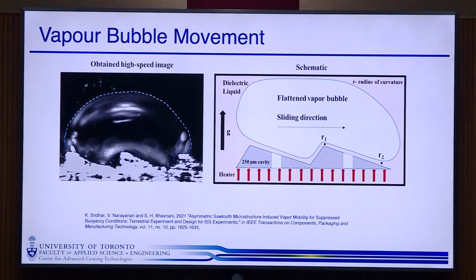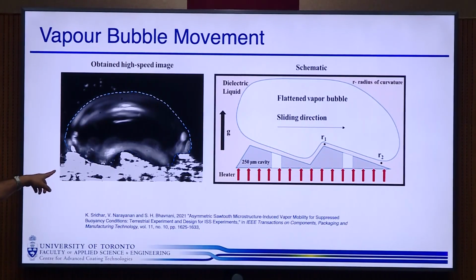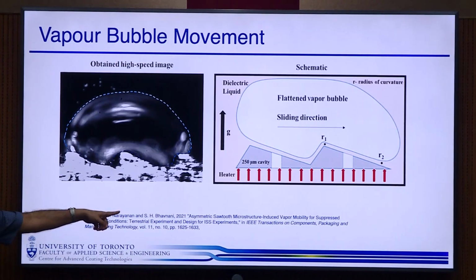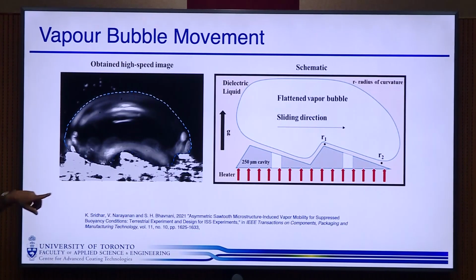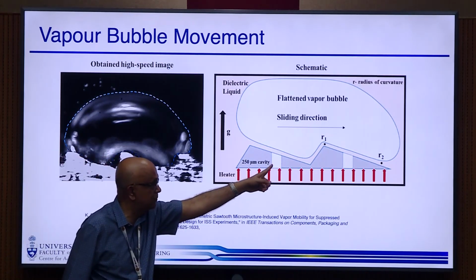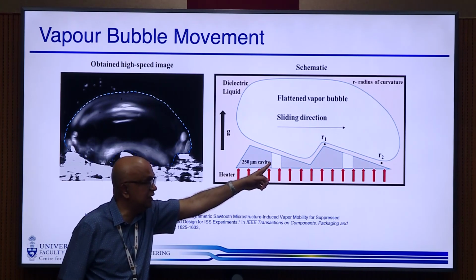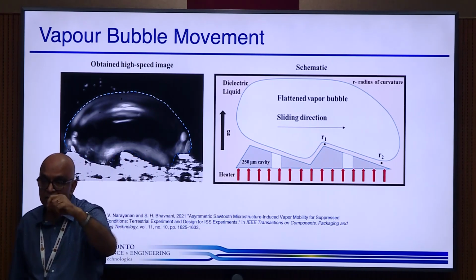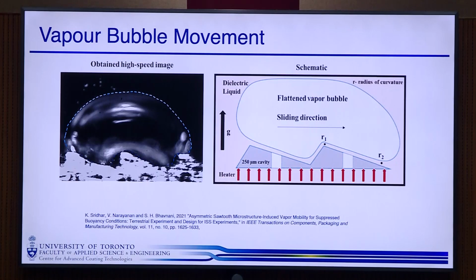So you can do this with a droplet. You can do this with a bubble. So this is another paper, from the group at Auburn University, and they're looking at bubbles in channels, and they've got this sawtooth structure, and they can drive the bubbles in one direction as well. So we said, okay, this looks like a nice idea. In this, by the way, for the boiling, they actually had to machine cavities inside each one of those to act as a nucleation site. If you just try and machine it, it's actually a very poor boiling surface.